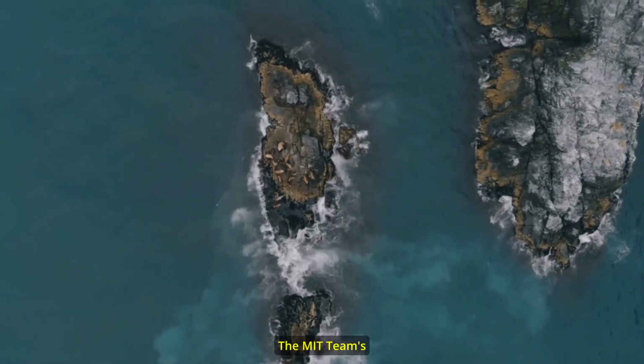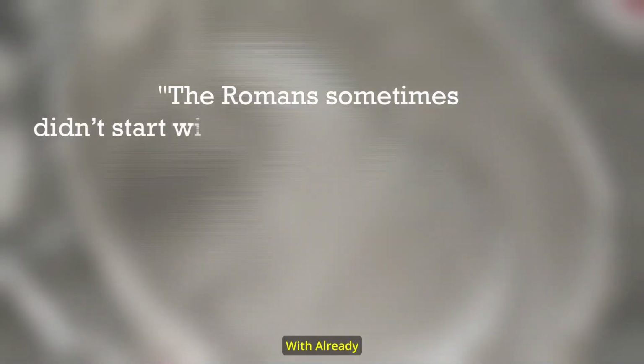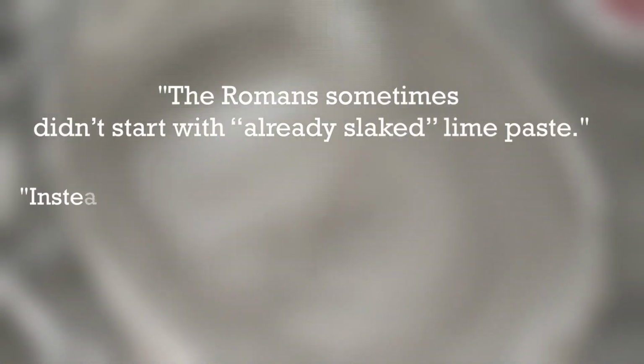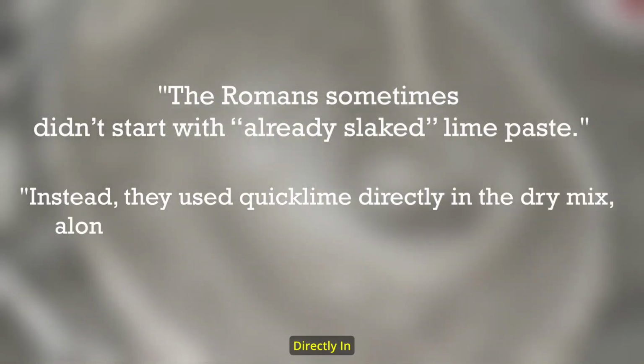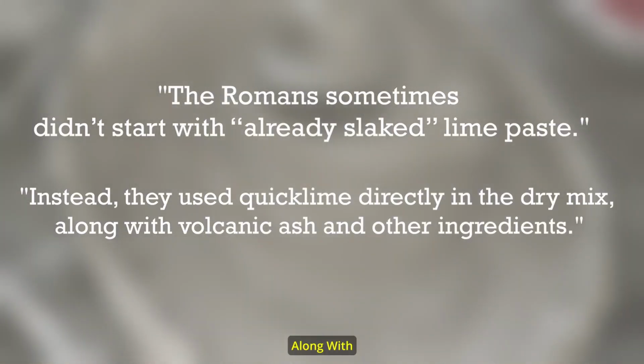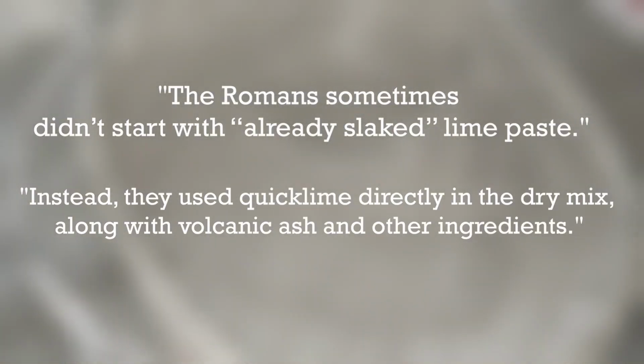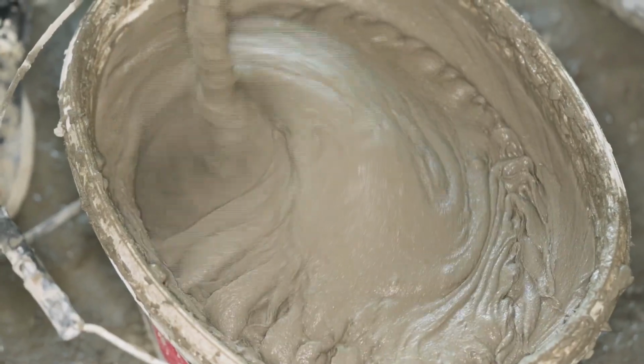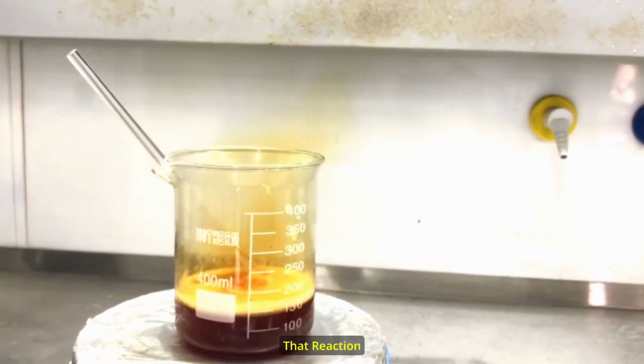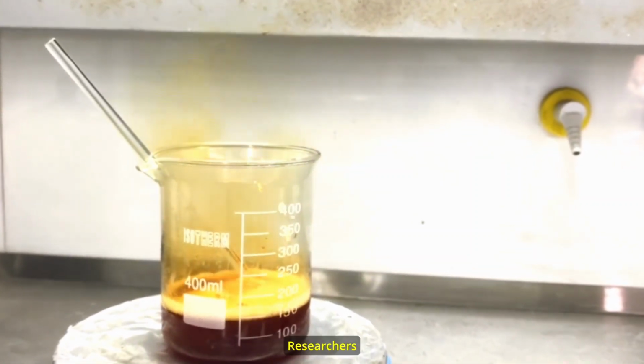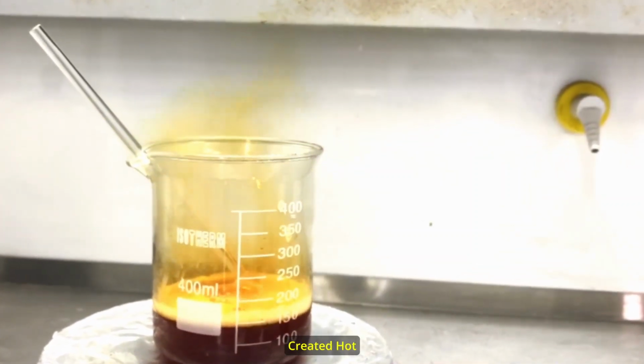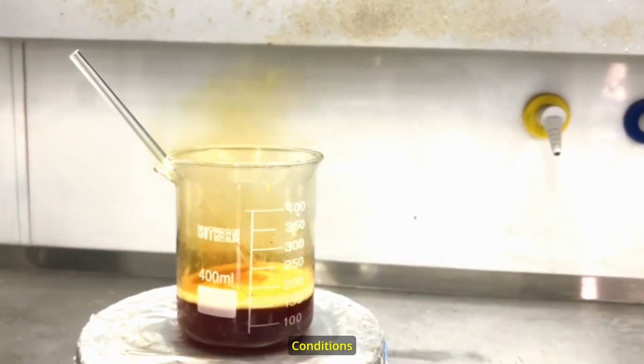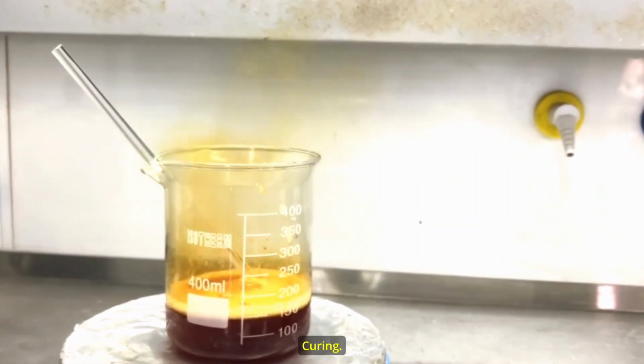The MIT team's answer was bold but simple. The Romans sometimes didn't start with already slaked lime paste. Instead, they used quicklime directly in the dry mix, along with volcanic ash and other ingredients. When water hit that dry mix, the quicklime reacted. That reaction produces heat. The researchers argued that heat created hot spots and unusual conditions during mixing and early curing.